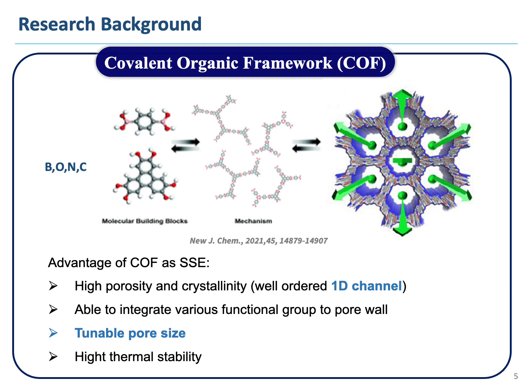In contrast to polymer electrolytes, which transport lithium ion via a hopping mechanism through the chain, well-aligned structure in COF serves as a host and provides a one-dimensional channel for lithium ion transport. Such structural characteristics show promise as a solid-state electrolyte for high-performance lithium ion battery.